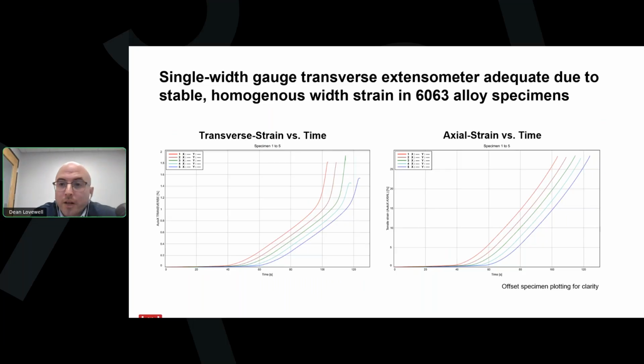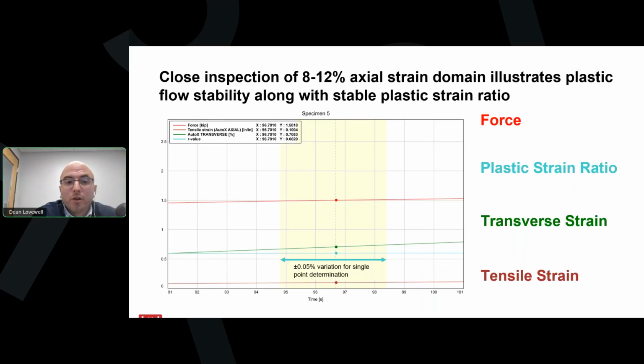And then looking at the transverse and tensile strain data individually, which we can do simply by creating additional Blue Hill charts, they're both smooth, which is how we get the smooth R-value behavior. And then looking very closely at the domain of the plastic strain ratio, we see that there's very little variation across this plot and almost no variation in the single point calculation.